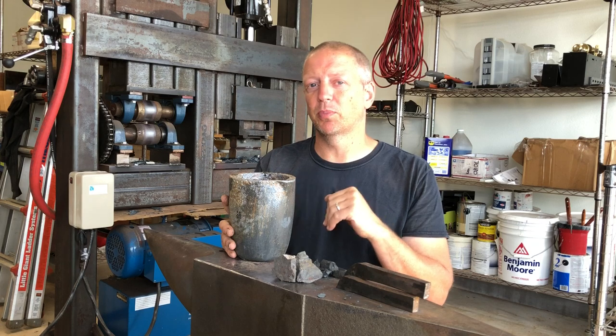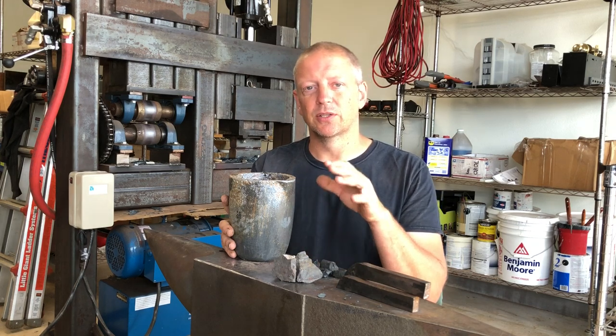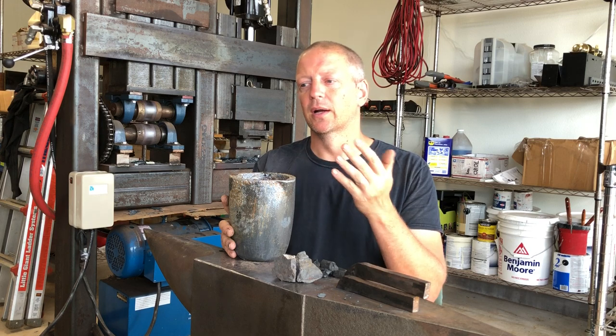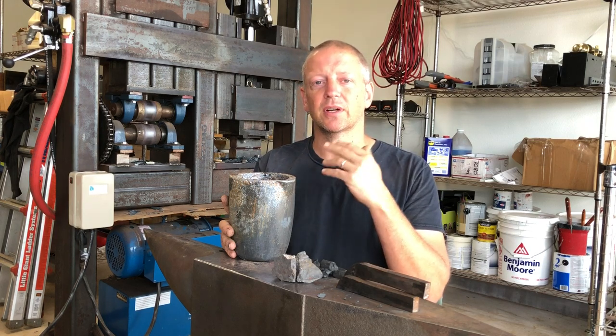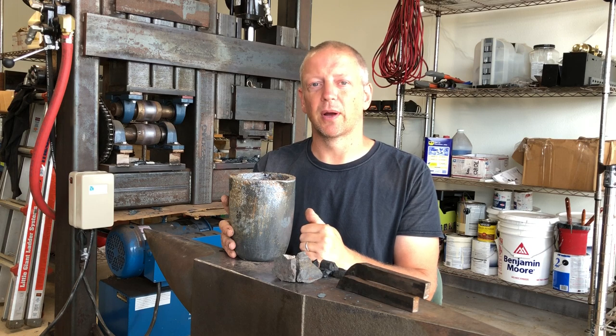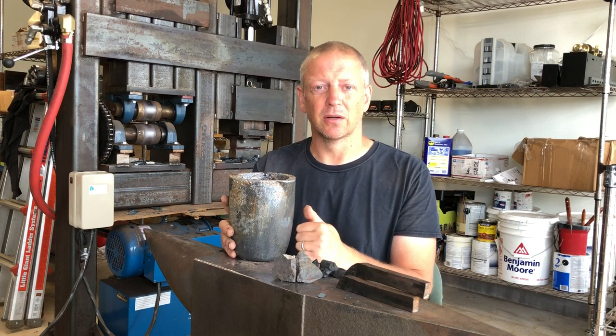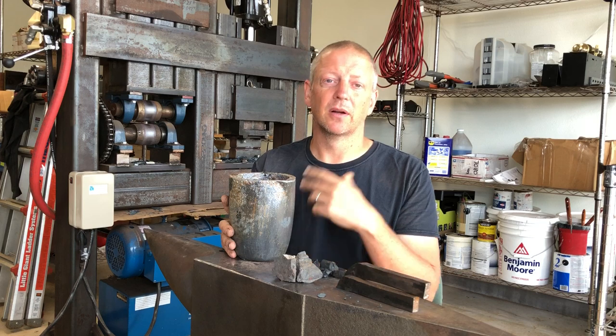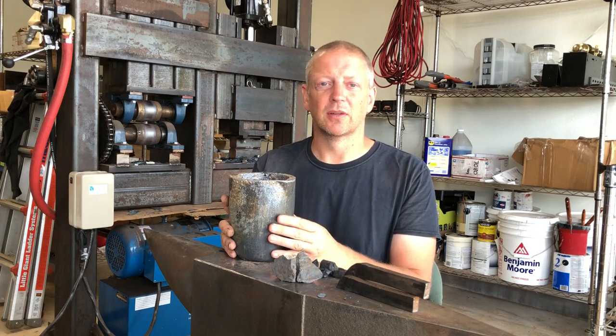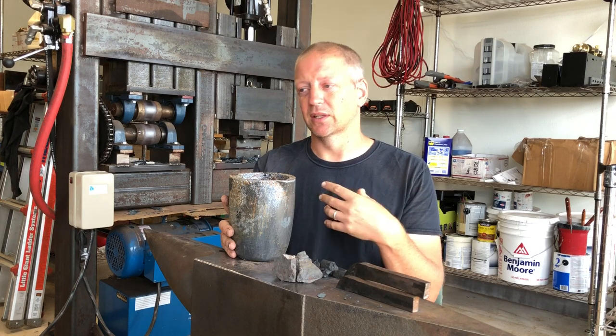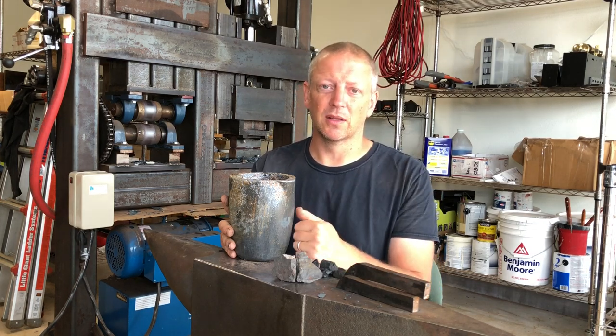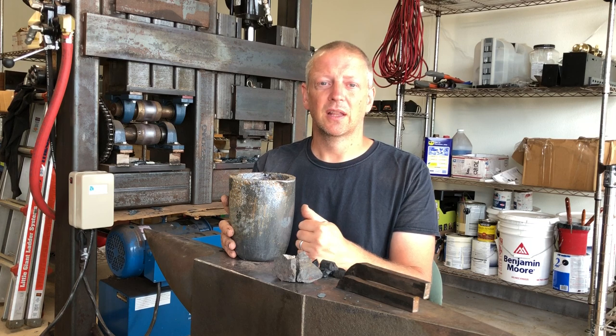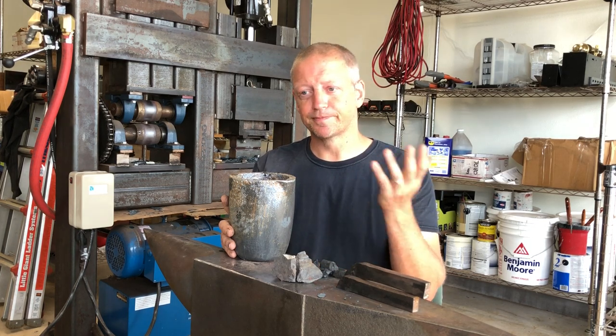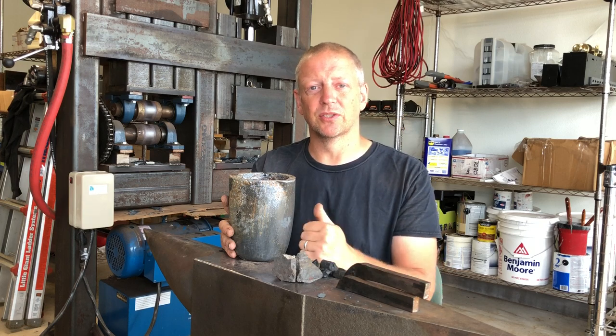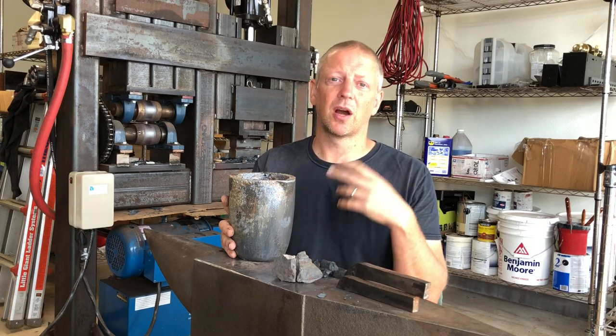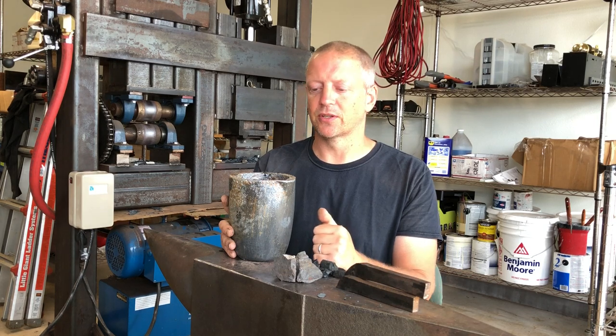And below 1.2% carbon, you're going to start to run into issues where you don't have enough carbides present to really get a good visible pattern. Also, the whole reason to make Wootz for most folks is they want the performance that those carbides provide. So once you're dropping into lower carbon levels, you really lose those carbides, you lose that particular characteristic.